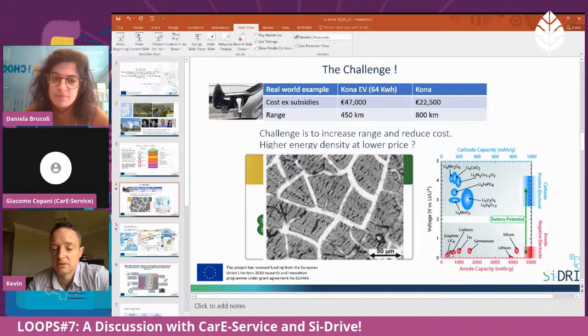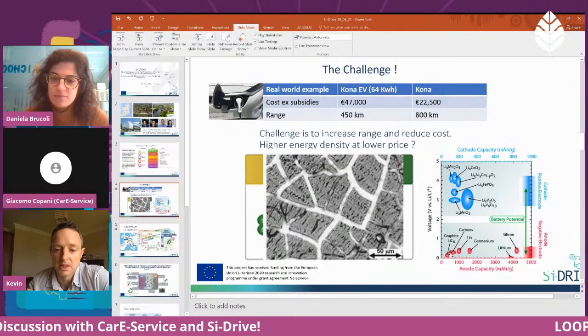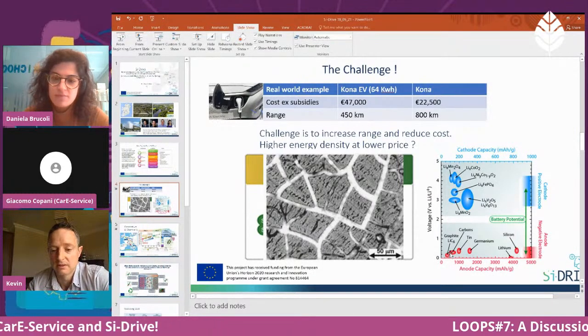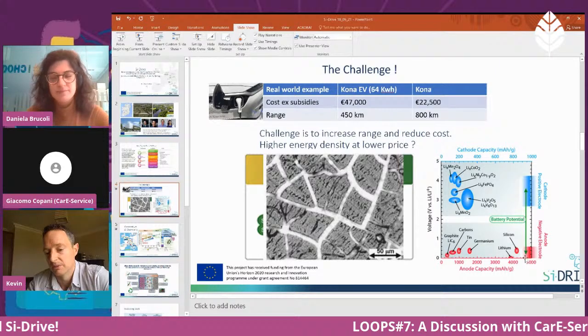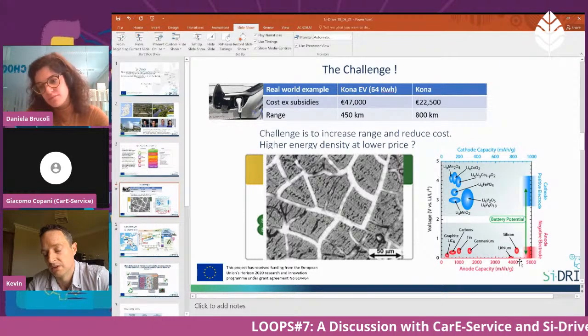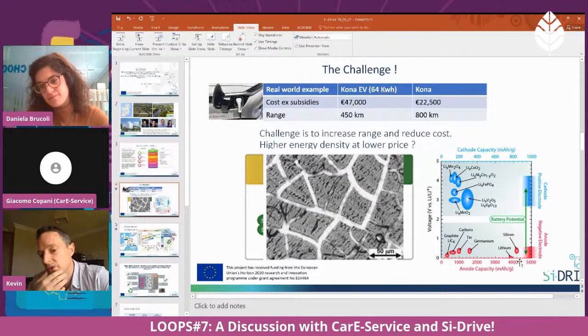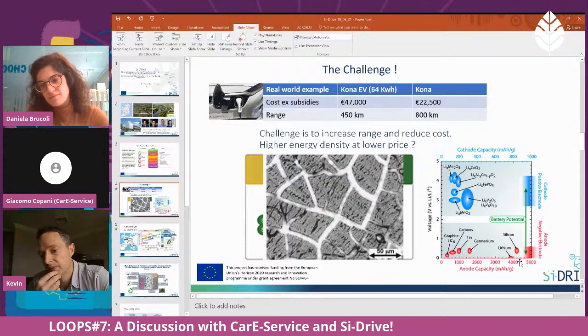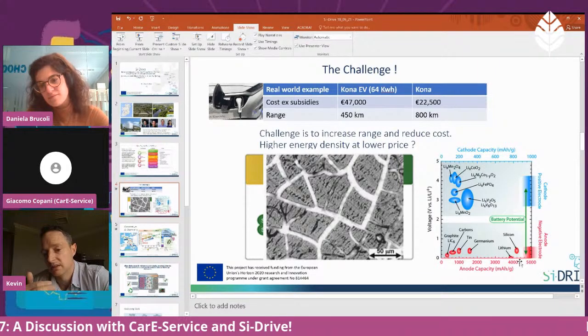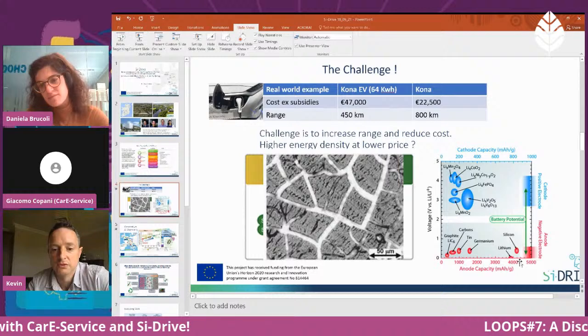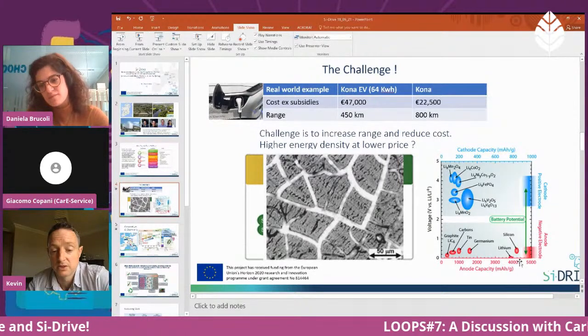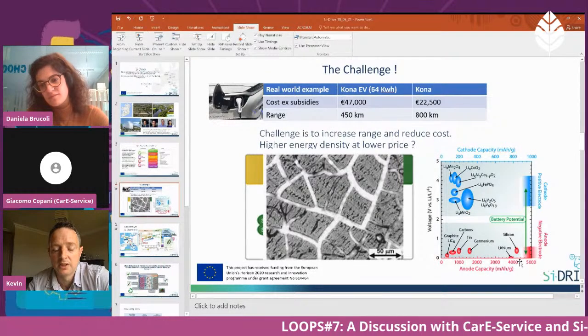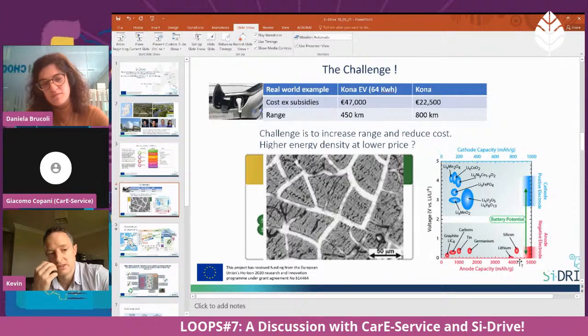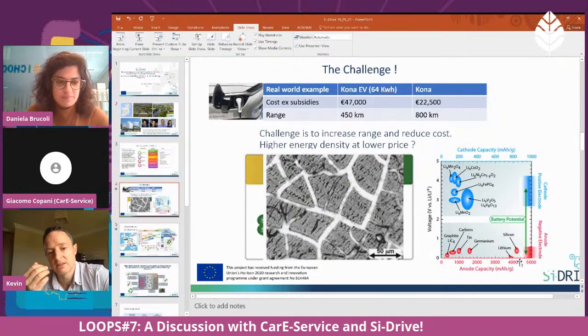And we can get a significant jump in capacity by moving from graphite to silicon, because silicon, if you see in the bottom right here, is over 4,200 milliamp hour per gram. And you also see that silicon has a relatively low voltage versus lithium plus, so it is a very good material for the anode. But the challenge with silicon is that